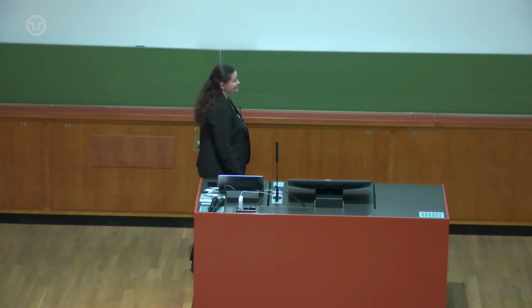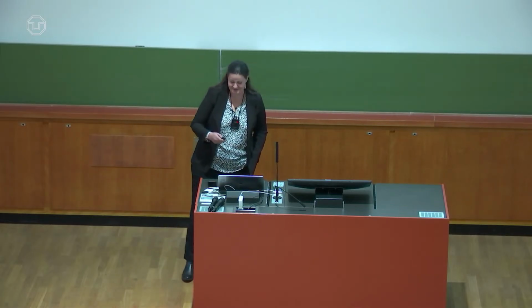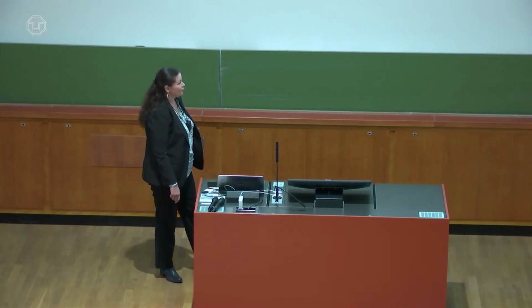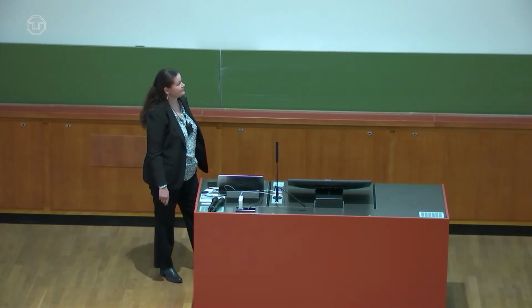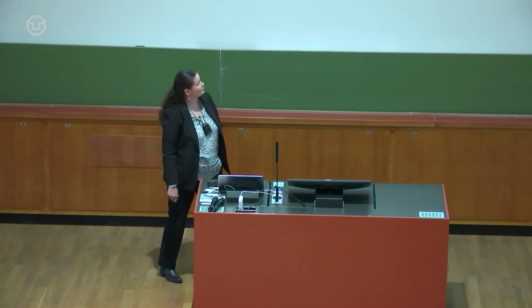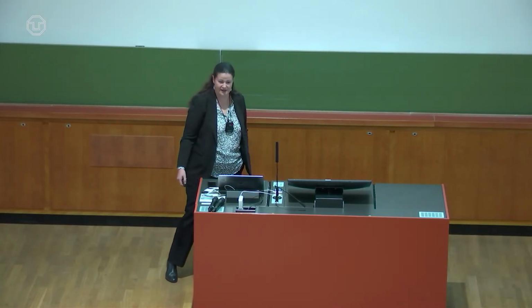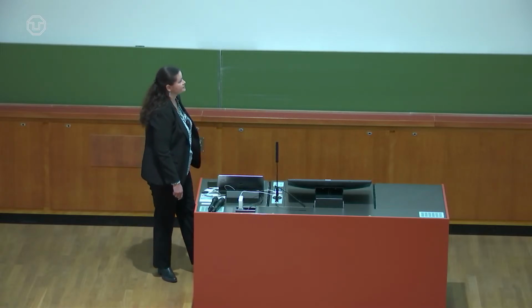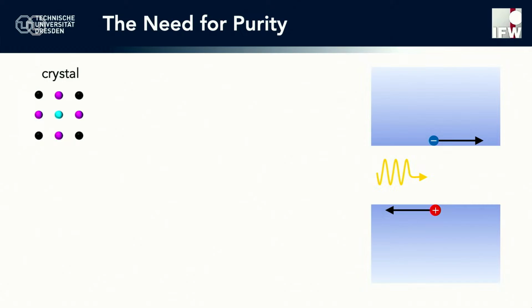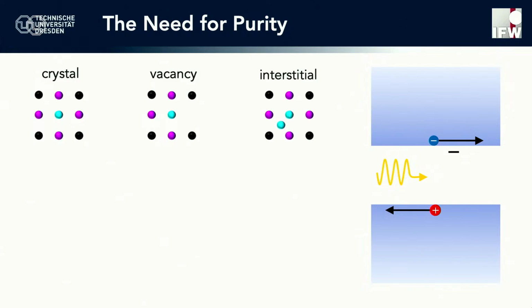Okay, and the interesting thing about perovskites is that we now can examine exactly what happens when we introduce defects into them. So again, we have a crystal structure, and we imagine that we shine light, and we generate charges which we can collect. What happens when we introduce defects? For example, a vacancy. In this case, a vacancy results only in a very shallow defect, not as deep as we had before. Alternatively, we could have an interstitial, which normally we would expect to lead to a deep defect in the middle of the gap.